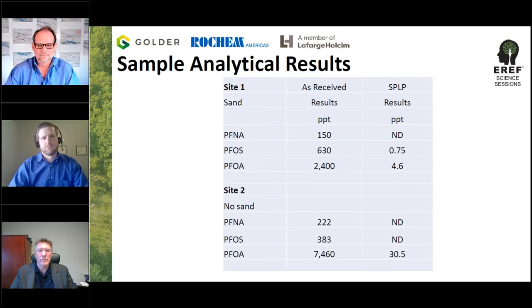But you can see in both cases there's a dramatic reduction in the amount of available PFAS as you solidify this stuff. On the first ones, you've got obviously 100% removal of the PFNA. The second one, 99.9% of the PFOS is removed, and the PFOA 99.8. And then on the second one, you have obviously 100% removal of PFNA, PFOS, and the PFOA is 99.6%. In all cases, except for that last PFOA one, they all meet Michigan drinking water standards. Now, you don't have to meet drinking water standards within a landfill because it's secure.